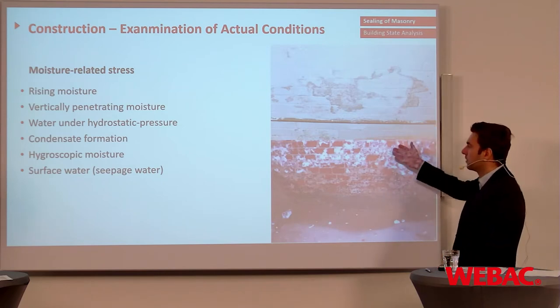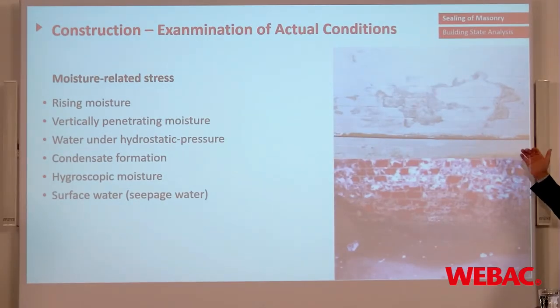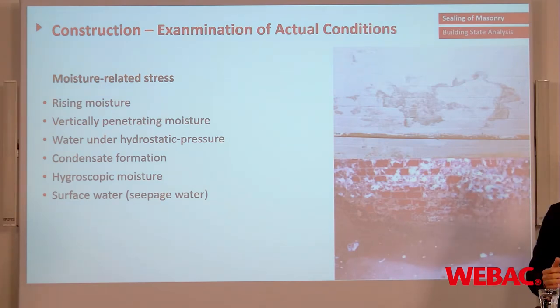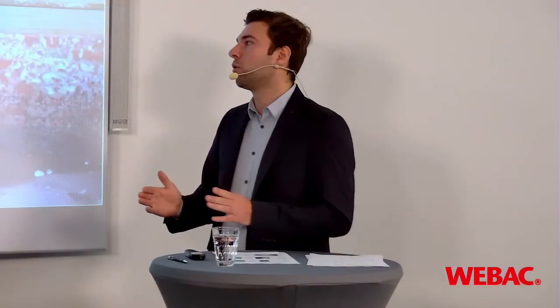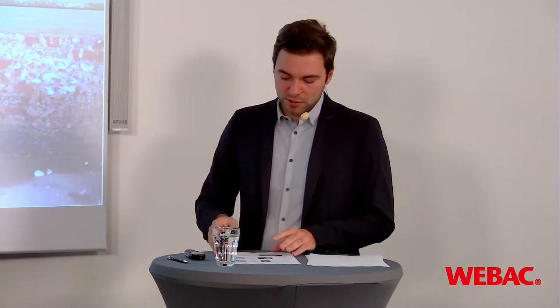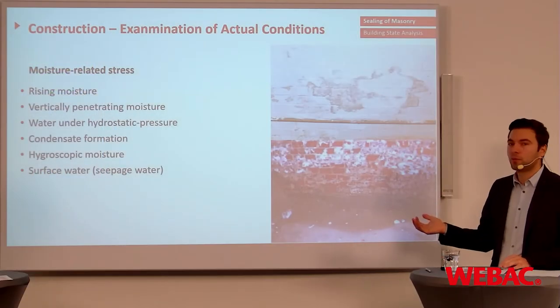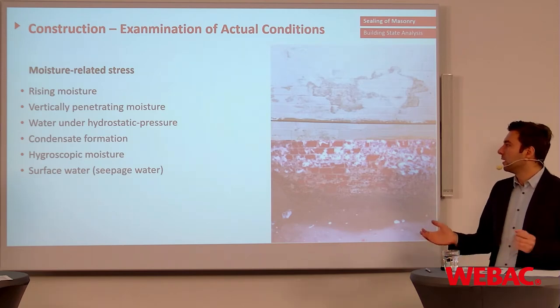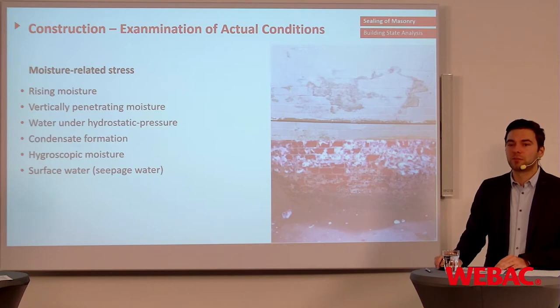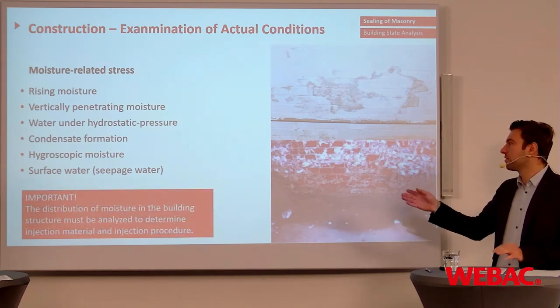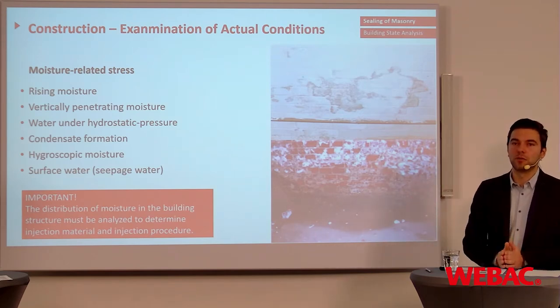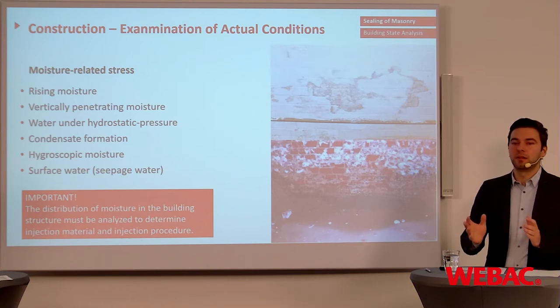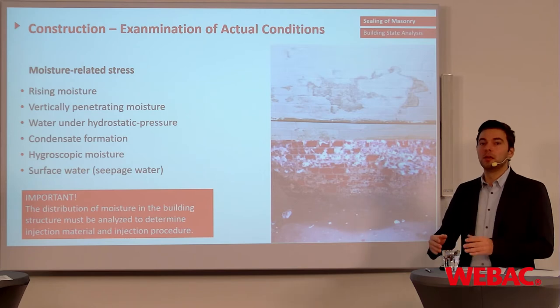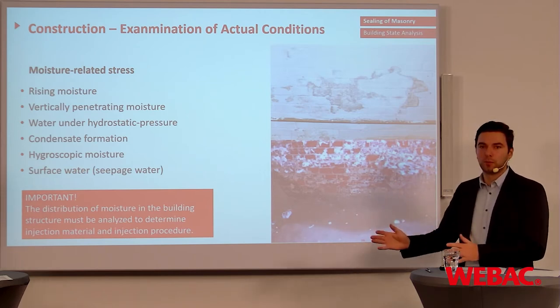Maybe this is a picture that you are aware of. You have a masonry with some salts on the surface, so you know that there is some trouble with moisture inside the building. But you have to be aware what kind of moisture you have. Is it rising moisture? Is it vertically penetrating moisture? Do you have hydrostatic pressure? Do you have condensate formations from inside because you're not venting enough? Do you have surface water? The distribution of the moisture inside the building is very important to know, because then you have to adapt your injection procedure and injection material to the kind of moisture stress you have in your building.